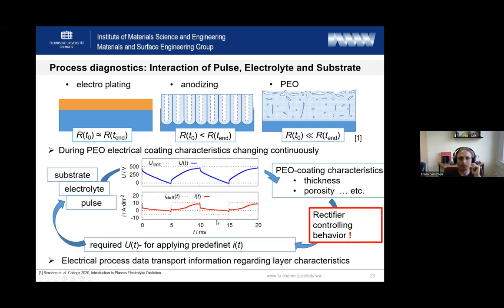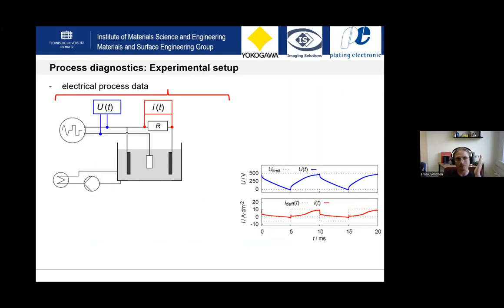So it doesn't make it easy, it makes it difficult to compare different experiments, and especially it's getting difficult to compare experiments of different working groups. But this interaction transports an unbelievable amount of information and gives you experimental access to what happens during the process. And for this, we built up our experimental setup. So we define an electrical pulse, and then we measure directly the voltage signal over the electrodes and the current signal over a measurement resistor, which we placed in our setup.